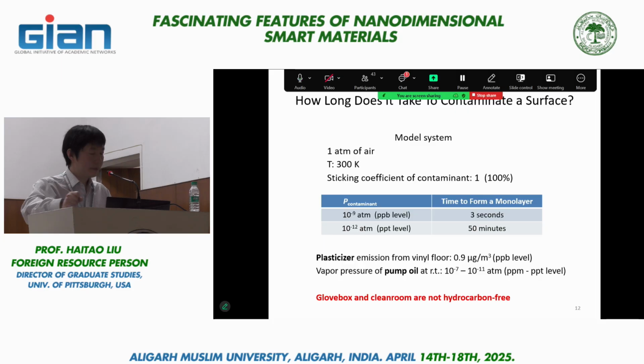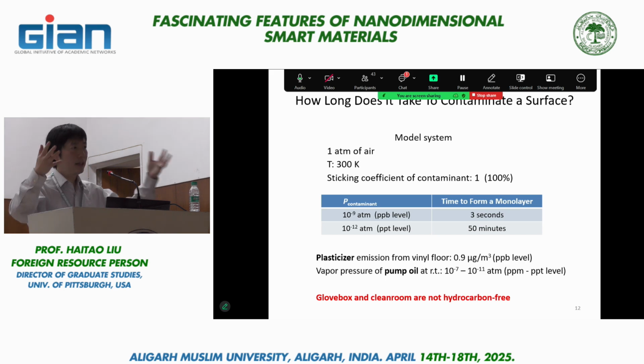If we do the wetting measurement right away on this clean surface, and that is the dotted data on the left-hand side, we can do the wetting measurement as soon as a couple of seconds after the exfoliation. In those cases, we measured a contact angle around 60 degrees. Now remember, for bulk graphite back in 1940, the contact angle reported was 85 to 86. Now we can indeed reproduce that data, and all we need to do is wait for an hour. Again, this 1 hour is within the kinetic ballpark number we estimated from the very simple gas kinetic theory.